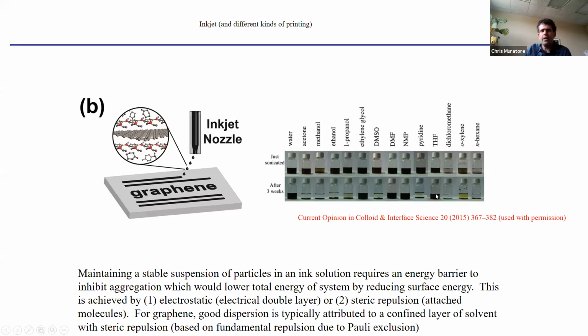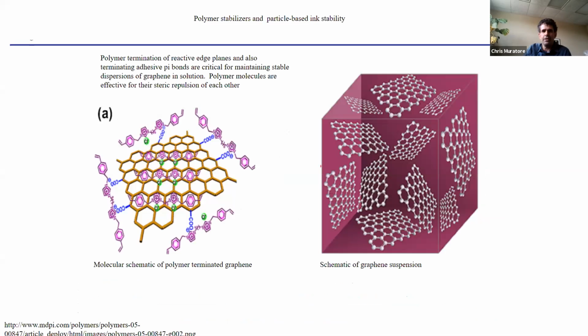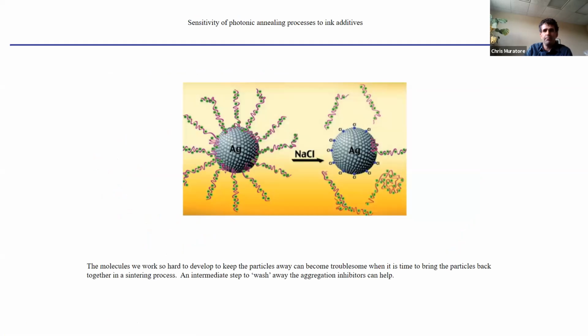There's other ways that you can induce stability in these suspensions. And there's costs and benefits associated with this. You can functionalize the particles with polymers, and you get this kind of steric repulsion, right? So you have these complicated arrays of atoms with electrostatic forces that will interact with adjacent flakes that are functionalized this way and push them apart. And this is a way to induce stability in the suspension, which is useful for a practical application like printing. So here's some other examples of nanoparticles that are functionalized to keep them from aggregating, right?